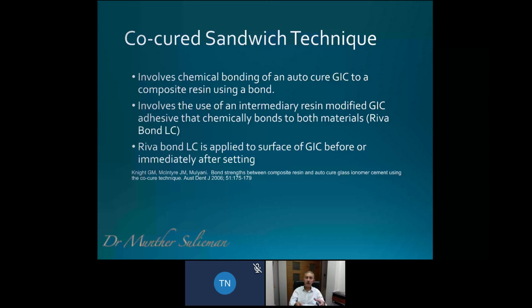heavy body self-cure, and then immediately when I'm doing that, as soon as I've put it in, I will use a resin modified glass ionomer bond, something like Riva Bond LC. It then actually bonds between the glass ionomer and the composite itself, and you do that straight while that is setting. You can do it afterwards if you wanted to, but I usually use it straight away because it helps me then pack down the glass ionomer quite nicely and wipe across the whole dentine, the enamel, what's left over with the Riva LC bond, and then I tend to cure.